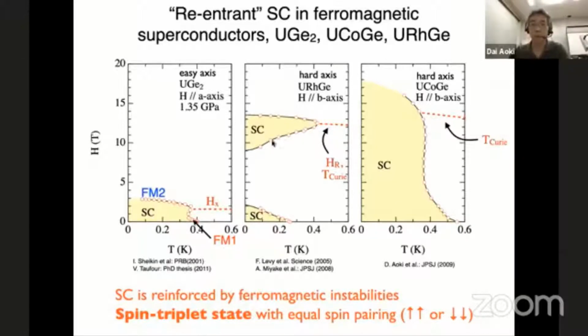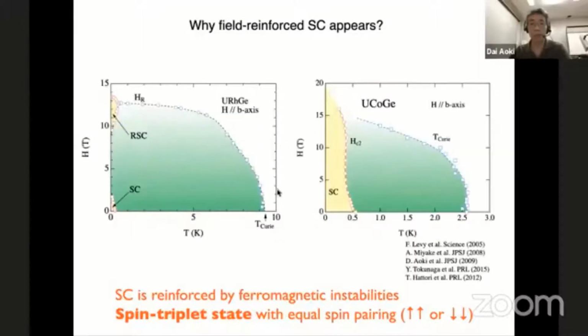And this reentrant superconductivity is strongly related to the ferromagnetism. So this graph shows the relation between the magnetism and reentrant superconductivity. Here you can see H versus T. In the case of uranium rhodium germanium, the Curie temperature is suppressed under magnetic field when the field is applied along the hard axis, the b axis. Then the Curie temperature is suppressed to 0. Then the reentrant superconductivity appears here.